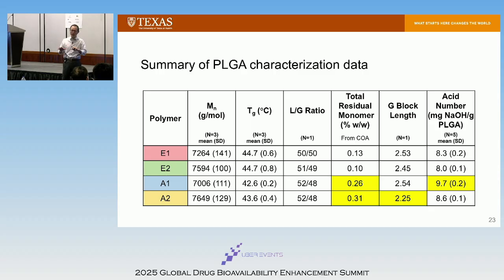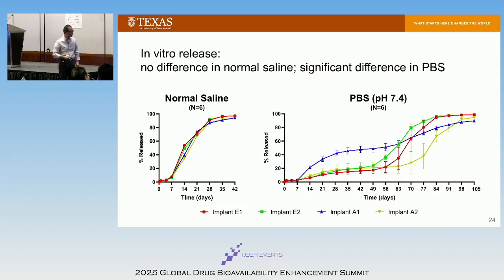And we actually have a way to control the porosities. If I change the die or the process temperature, I can make the front side more restrictive. The more restrictive they are, my pores get smaller. So this is a way to control. We can control from 5% all the way to 25% porosity. And this was later on, after the fact, we realized, oh wow, with the extrusion process, whatever your starting material is, most likely ends up staying, and they will impact drug release. So let's look at the drug release.